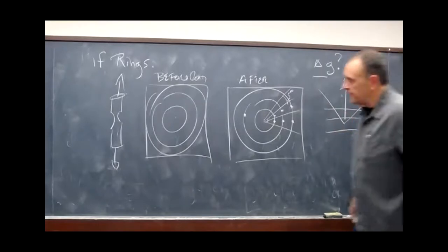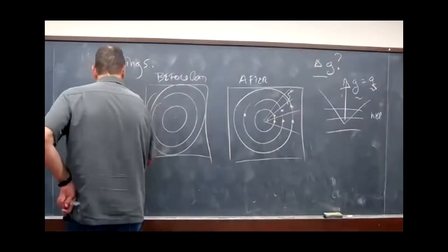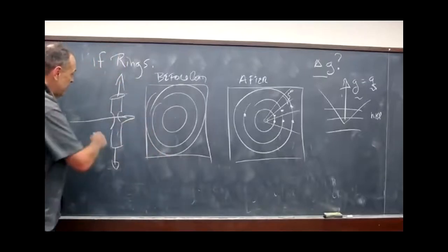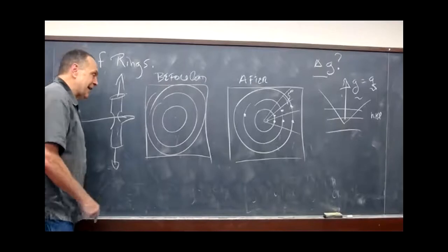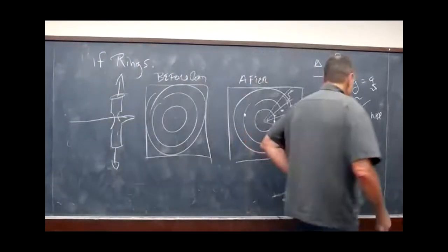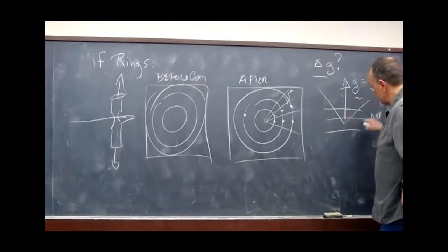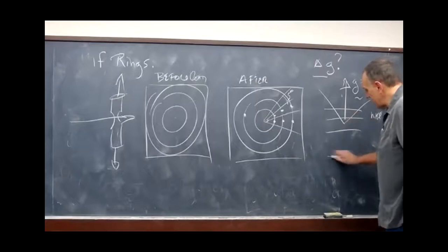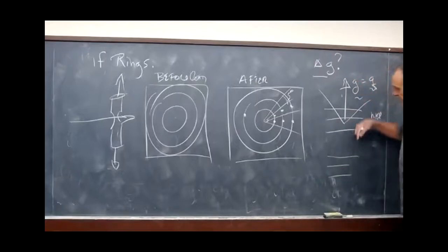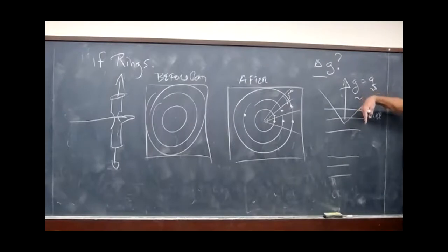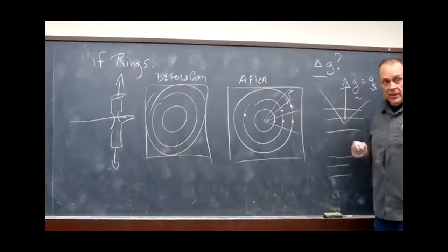Okay, so X-ray goes through the sample, and it's asking everybody. Remember, this is a monochromatic experiment. It's going through and asking everybody, are you oriented like this? And some are. So there's not just one crystal like this, right? Because just because I have this HKL oriented like this, I can have another crystal that's rotated about this scattering vector. So this has one matrix, this has another rotation, they're completely different. Now they're related, and Darren may or may not talk about how they are related and how they look in orientation space.